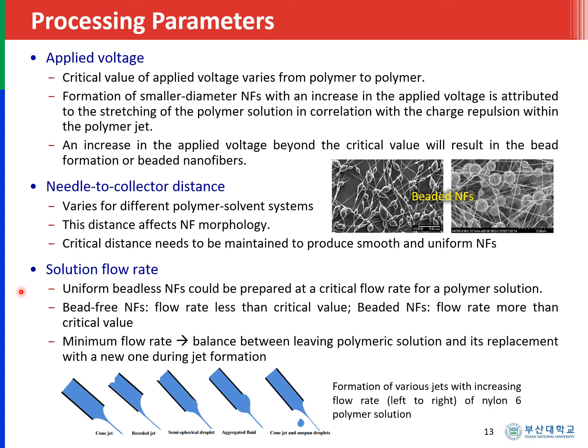Like the two other variables, there's also a critical value for flow rate for a certain polymer solution. If your target, of course, is a quality nanofiber, then it should be uniform and beadless. Then you need to determine that critical flow rate. If the flow rate is less than that critical value, then you would form uniform beadless nanofibers. However, if the flow rate goes beyond that critical value, then beaded nanofibers will be produced. Since we are targeting quality nanofibers, we don't want beaded nanofibers, so we need to determine the minimum flow rate at which there would be a balance between leaving polymeric solution and its replacement with a new one during jet formation.